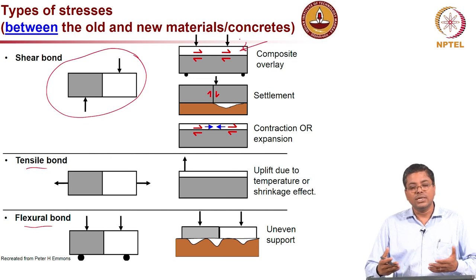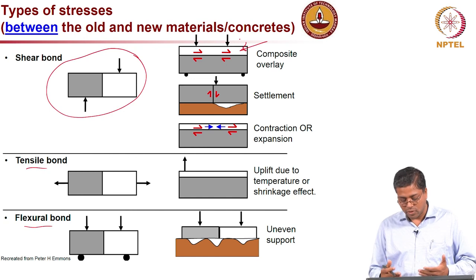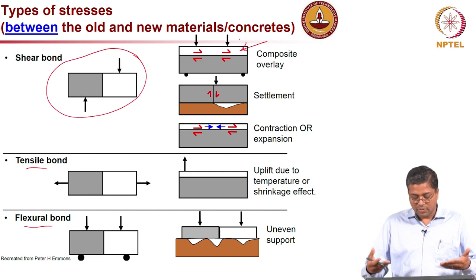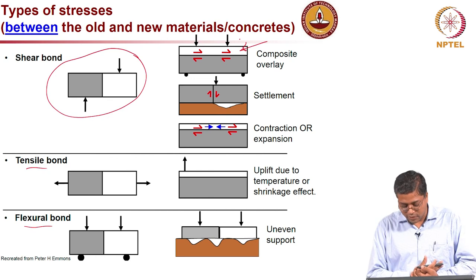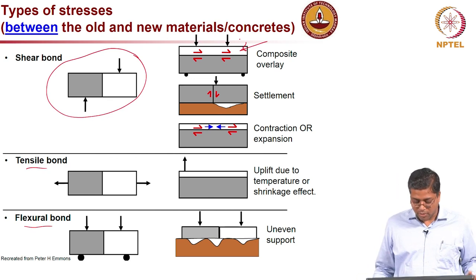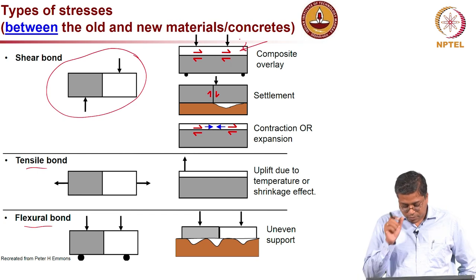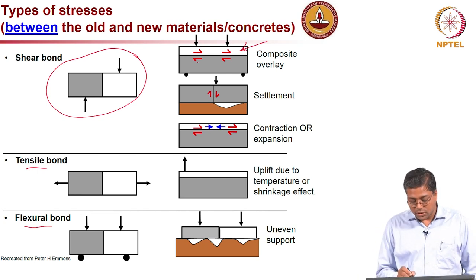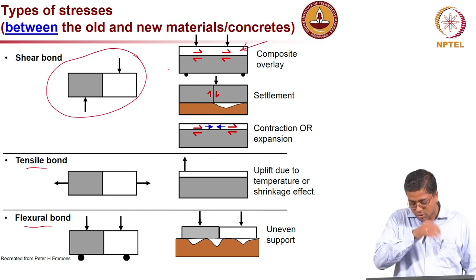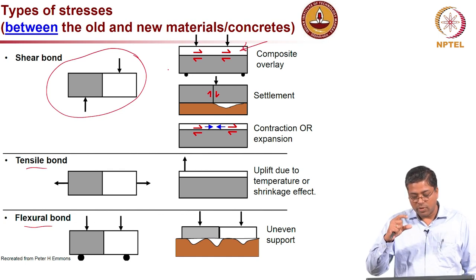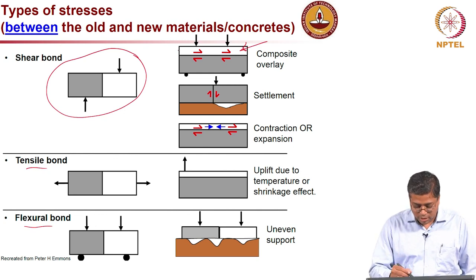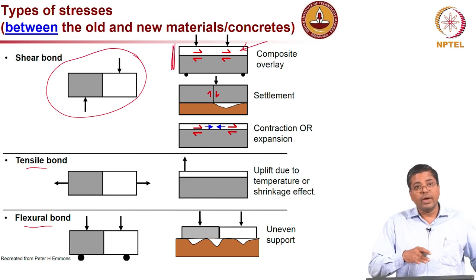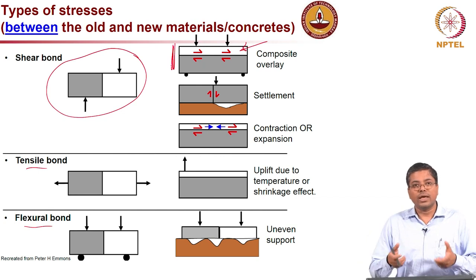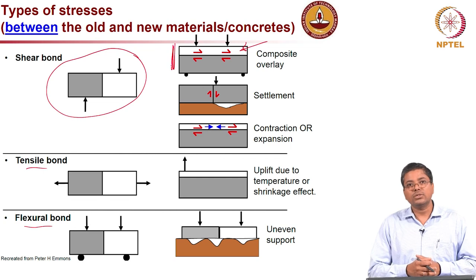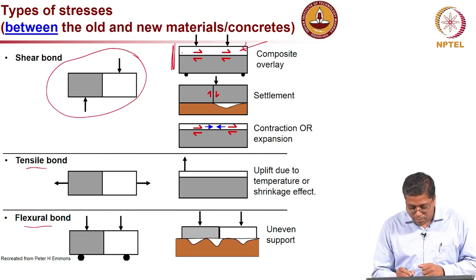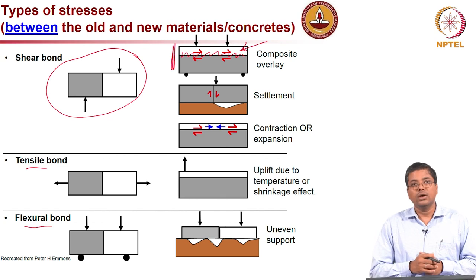Otherwise you will probably see delamination, not because of corrosion, but because in some cases even water can get in, and then it will create significant debonding of the overlay. I have seen it in many places. And also the flexural action, or the bending: both the overlay and the substrate concrete, or the deck itself, should bend together. It should not bend like a laminated system; both should act together. For that to happen, the bond between these two is very important.